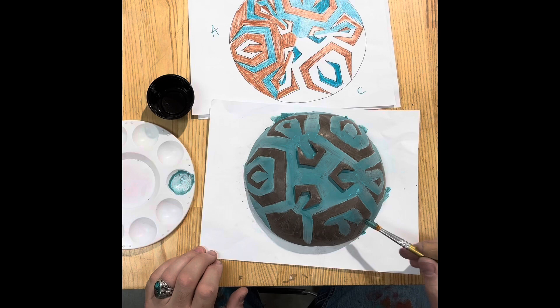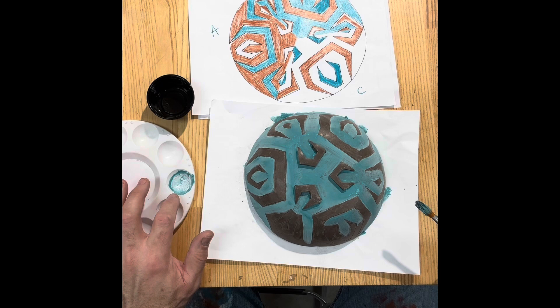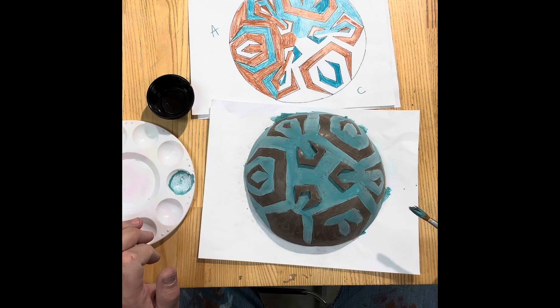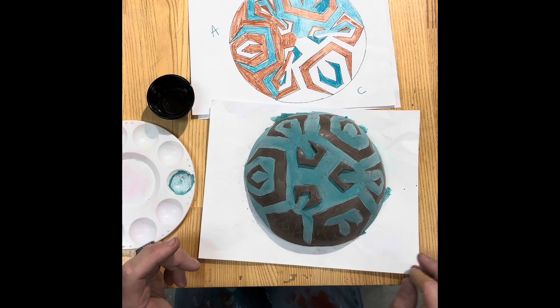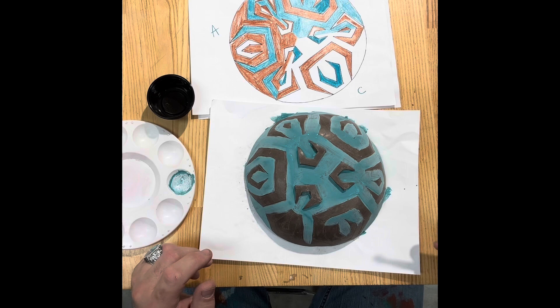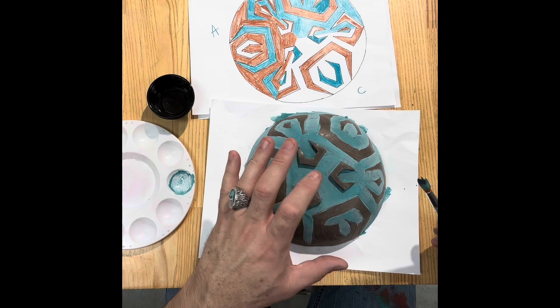Small break in the time lapse. I wanted to show that I am a little bit messy in some areas. I can go back in after I've painted all three layers — I think I'm going to do three layers to make sure it's opaque. I also almost finished my bowl's first layer with just a small cup of glaze from the palette. Try to conserve glaze without skimping — do at least two layers, because one will be see-through. Two will most likely be opaque; three definitely will.